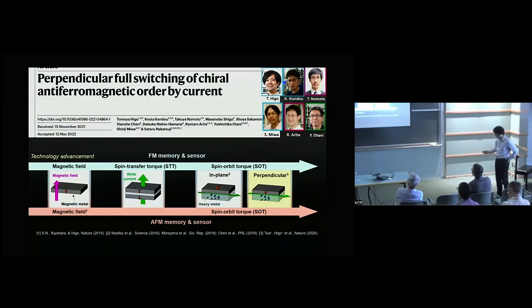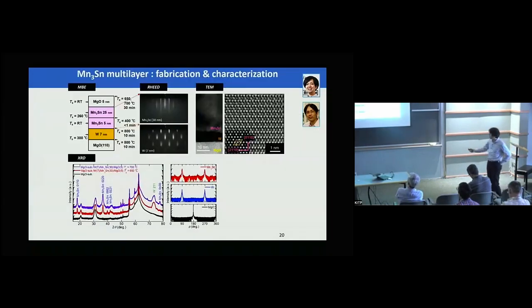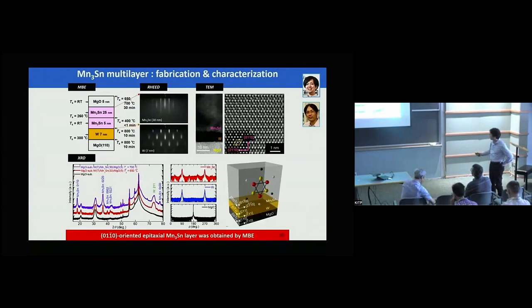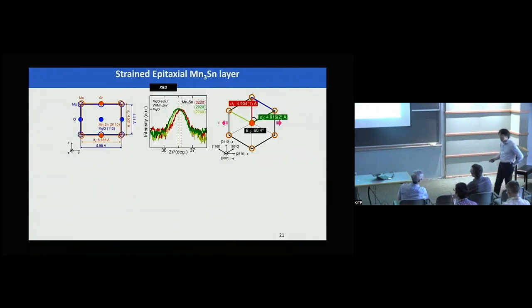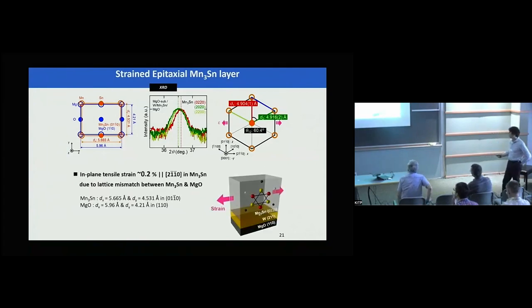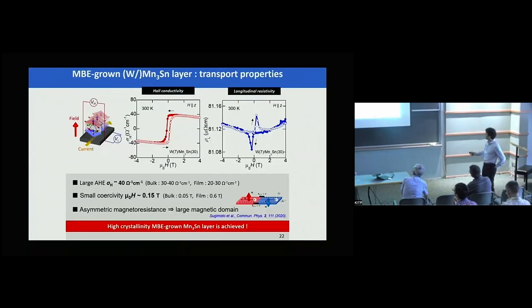Full switching is very important for antiferromagnetic order. So these are the experimental details. I maybe cannot focus so much on this with the time constraint. But the point I would like to make here is that by using molecular beam epitaxy, we made this perpendicular magnetic switching layer perpendicular to the MgO. The Kagome layer is perpendicular to MgO. Of course, there is the lattice mismatch between MgO and the magnetic switching layer. That actually provides a 0.2% tensile strain, which turned out to be later important for us to consider piezomagnetism. And the Hall conductivity and the coercivity and so on are quite close to the bulk system. So a very high quality thin film is available.